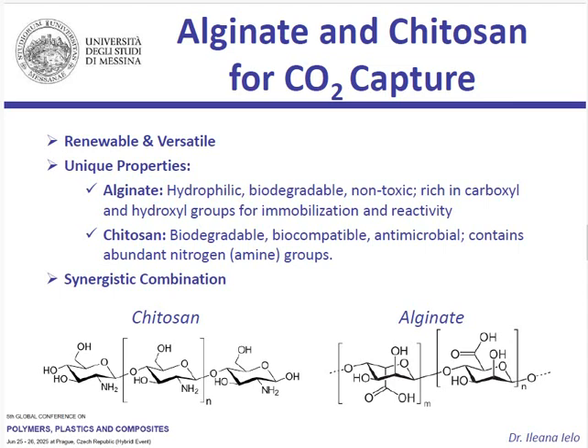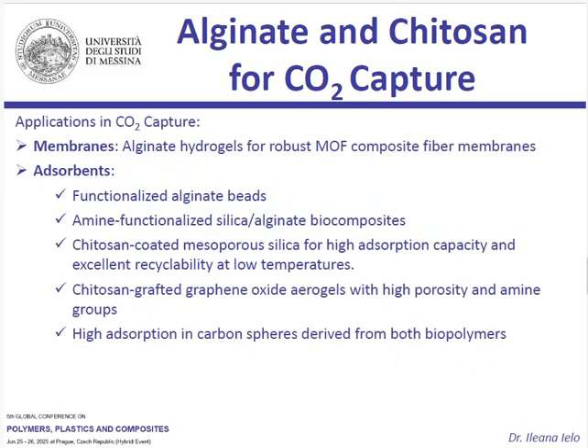A particularly powerful approach is their synergistic combination. Alginate and chitosan are often used together, leveraging their complementary electrostatic properties to create materials with increased stability and durability. In the context of CO2 capture, their applications are diverse and effective. In membranes, alginate hydrogels have been successfully used to prepare robust MOF composite fiber membranes, demonstrating excellent separation ratios for gases like hydrogen and carbon dioxide.